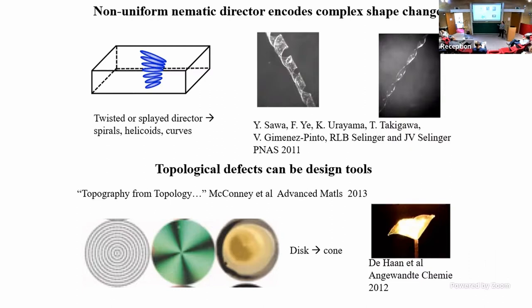What happens when you take this thing, so you form the material between two pieces of glass, you remove, now you have a little thin film polymer with this twist across it. When you remove the two pieces of glass, the material, if it's still at the same temperature where it was cross-linked, it'll be just flat. From that, we typically cut strips, and the strips can be cut east-west, north-south, or at any angle, and depending on what angle we cut, you can get all kinds of different shapes. So you can get something hollow that looks like the tube that your paper towels come on, if you opened it up, or it can actually twist like a piece of rotini.